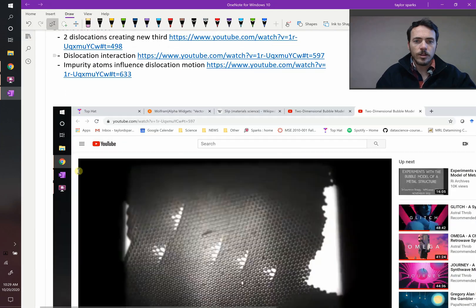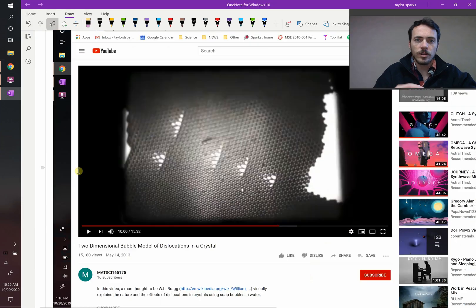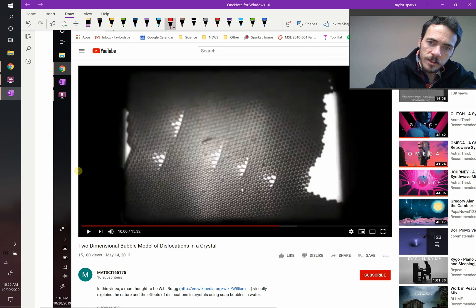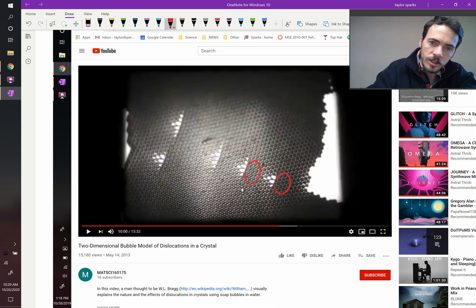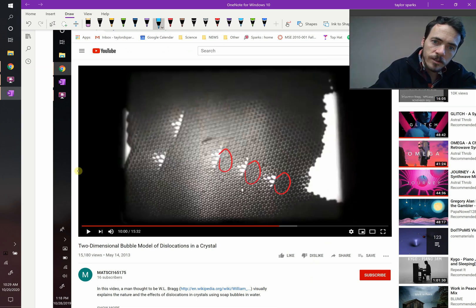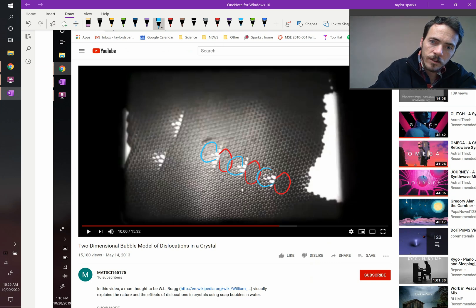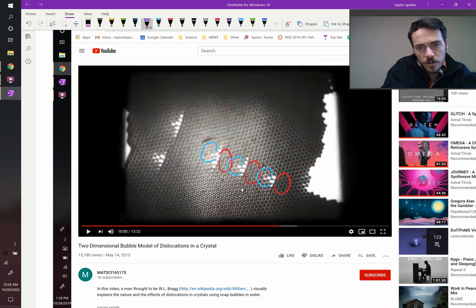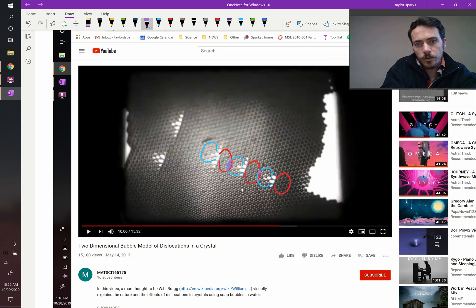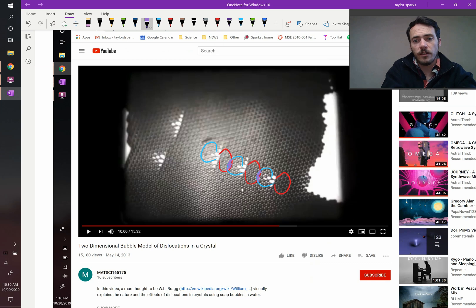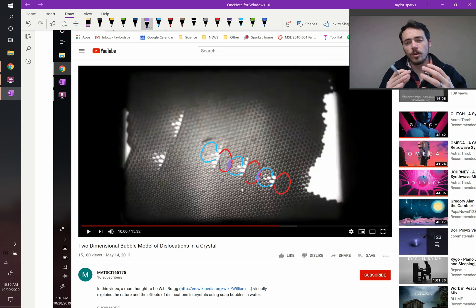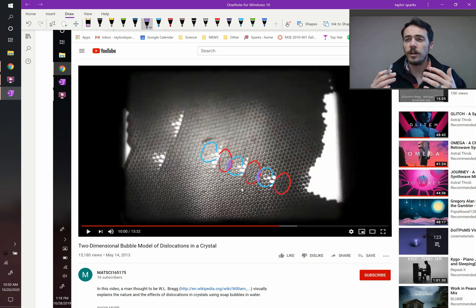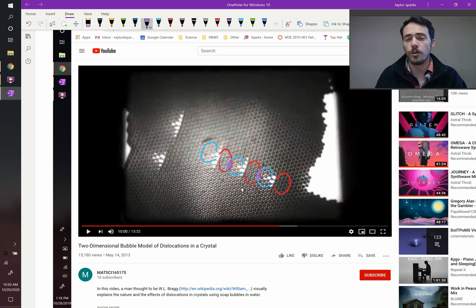So why are they stacking vertically? Again, you could picture it like this. Each one of these has compression here, compression here, compression here, tension here, tension here, tension here. And so you get these regions of your diagram where these things overlap with one another. The tension and the compression regions overlapping is good. That's what the crystal wants to have happen is those things overlapping because if you're going to be strained two different types, when you put them together, it reduces the overall strain.